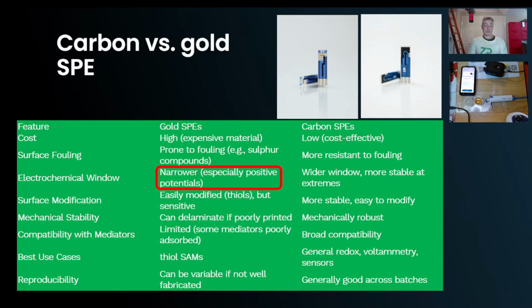Whereas I'd argue carbon has a much wider window of electrochemical stability. We can apply higher positive and negative potentials, and carbon is inert. One of the advantages of gold is you can easily modify it with thiols. Earlier on I put that as a disadvantage because it will absorb sulphur molecules from the atmosphere. The same means that you can also use thiols in making self-assembled monolayers, which I'll get to in a bit. So it is easy to modify.